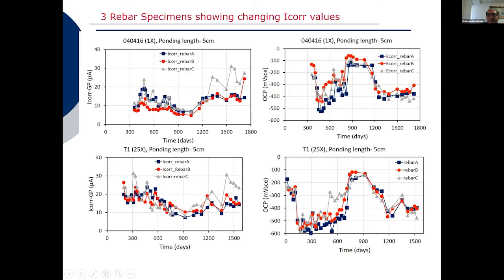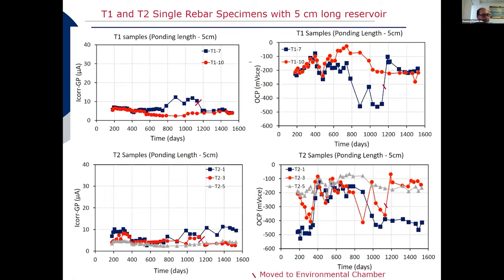Interestingly, on the right, you see the potential, how it changed, and the potentials went towards more negative values and remained in the active environment. Then we dried the samples a little bit, left them, I guess, a winter without adding moisture, and the values went to more positive values, but then it became more active again for this particular specimen. So for time constraints, I'm going to move a little bit faster.